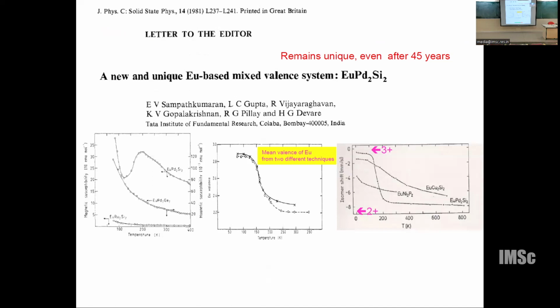We discovered a new material, probably the second one, in the europium system. Look at the susceptibility of this compound. You have to be careful with the scale. This is a divalent system, so you look at this side scale. This is the trivalent system, look at this scale. For our compound, this curve should lie somewhere here, so you find an intermediate susceptibility. And there's a huge drop in susceptibility at some temperature. Forget that upturn, it is due to impurity. Later we got better material where it is virtually negligible, so susceptibility becomes basically constant at low temperature.